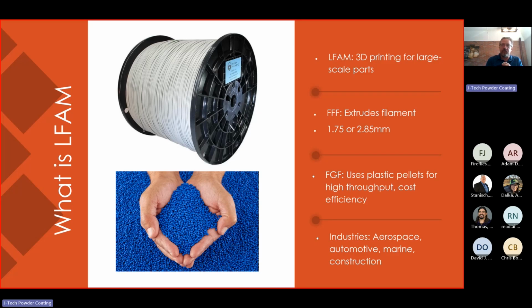So this is scaling up desktop printing. A lot of these machines are using a 2.85 millimeter filament, but some are running 1.75, and they use a high flow hot end to deposit material faster for really large parts. FGF, on the other hand, uses plastic pellets, as shown in the bottom picture. These pellets are similar to injection molding, allowing for higher material throughput and lower costs. Commercially available pellet extruders range from about 1 kilogram an hour up to 225 kilograms per hour. The choice between FFF and FGF really depends on your part size, material needs, and budget.